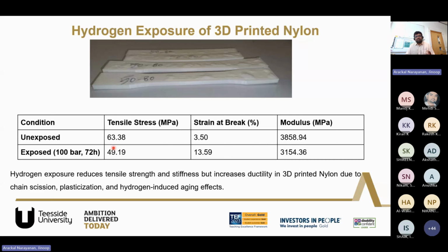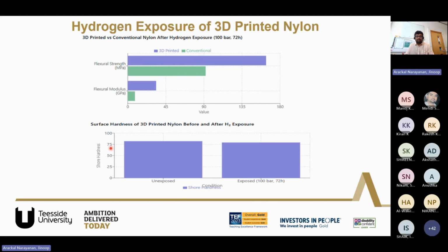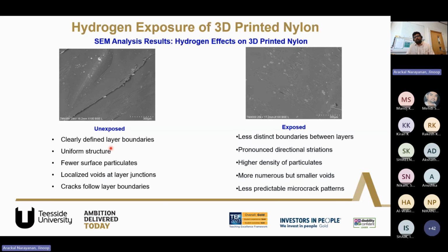It's mainly because of the change in plasticization and hydrogen-induced aging effects that has a reduction, with the breaking of the chemical bonds to some extent. But we are still working on this because this is one of the studies that we did. We are still working to understand more in depth how we can control this, or how we can improve the hydrogen exposure resistance of these materials. So we observed that the reduction in Shore hardness and the flexural strength was also there, and we could see a lot of voids and particulates in the samples.